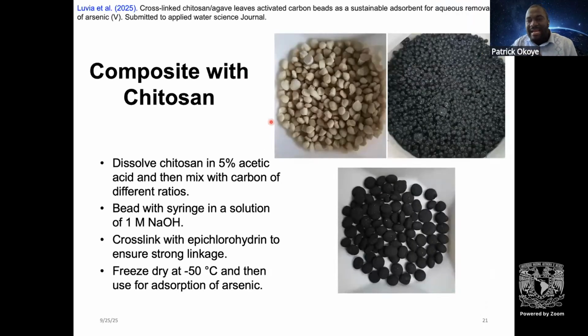So we combine this chitosan by dissolving it in 5% acetic acid and then mixing it with carbon of different ratios. And then we use a syringe to bead and form these small beads of chitosan in 1 molar sodium hydroxide. And then we obtain this form of the material.